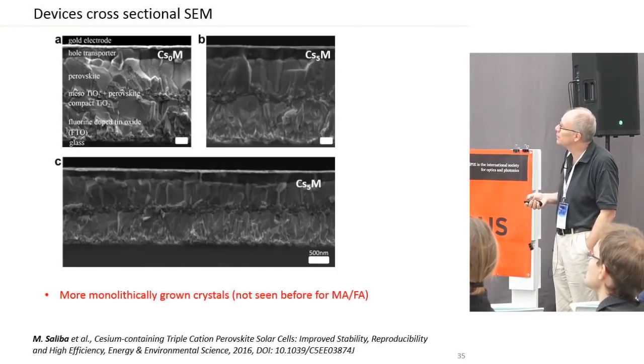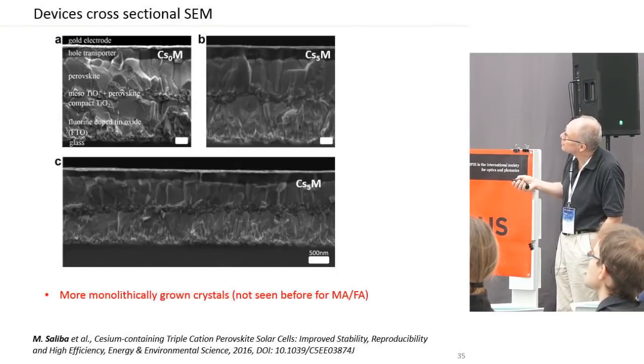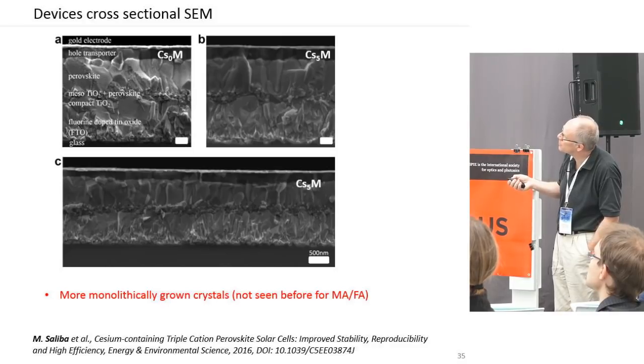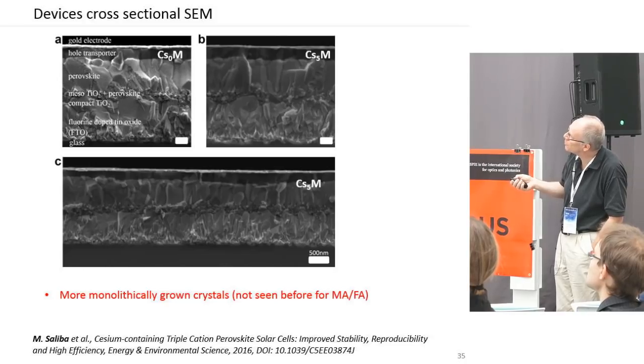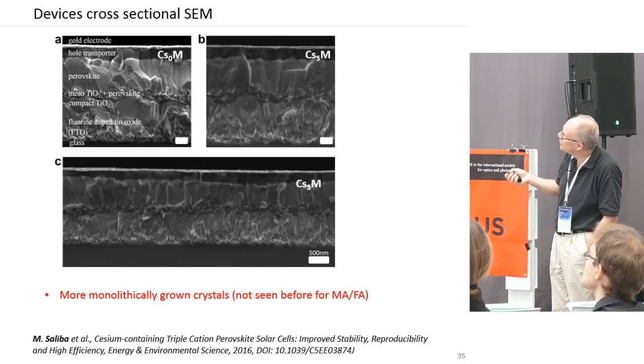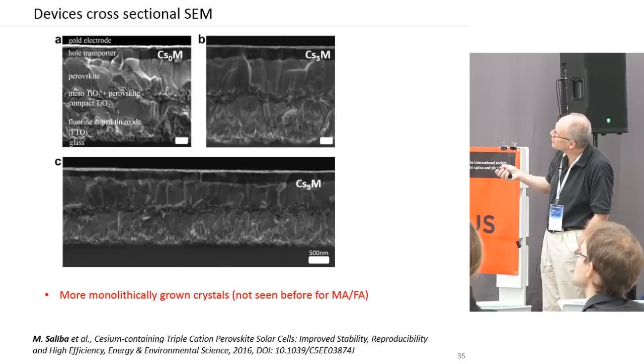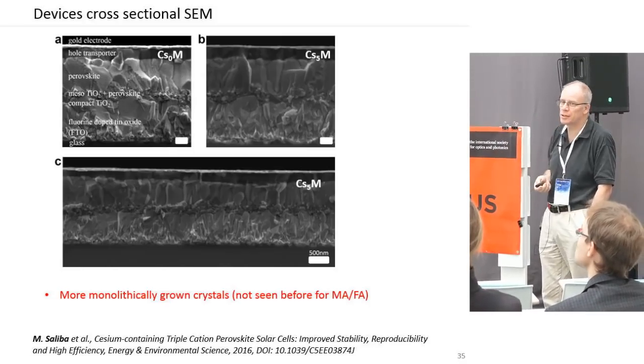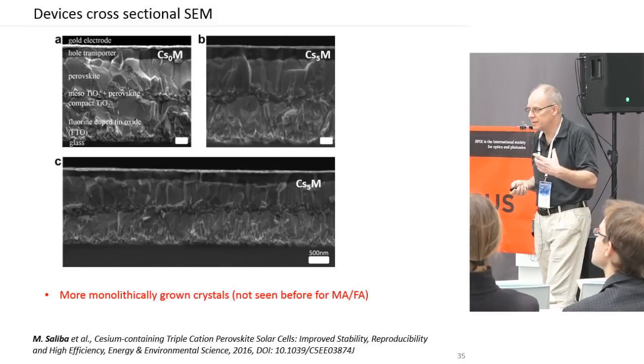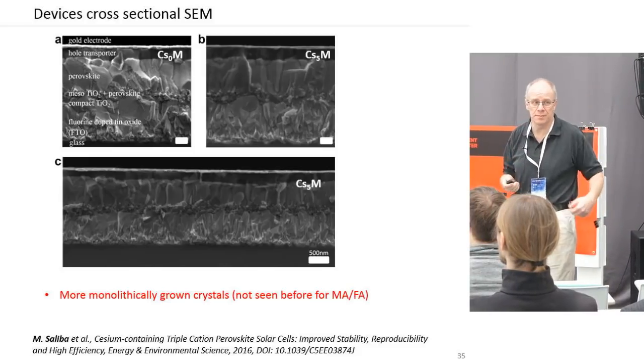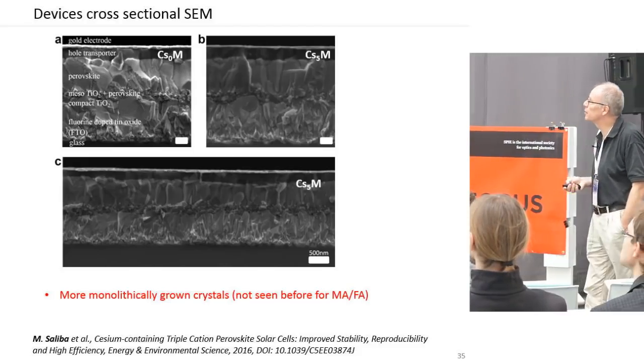And we can say that one reason is that this is a cross-section SEM, and you have the perovskite layer with the grains, the crystallites like this, and what you don't want to see is a lot of grains with these grain boundaries where you may have recombination losses. So adding 5% cesium makes the perovskite film much more perfect, let's say, without grain boundaries and higher quality. The reason for that is still to be studied, let's say. But this mixed is a strategy we are working with.